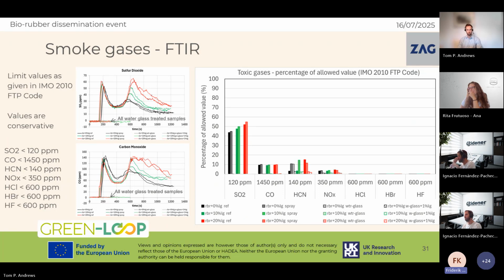So here we have 7 gases, but actually we tested for 22 gases. These are the exposed results, because these were those that were actually seen on FTIR. The others were even less than virtually not detected. And the criteria taken into account here is the criteria for shipbuilding industry, which is a little bit more stringent than one would expect for buildings.